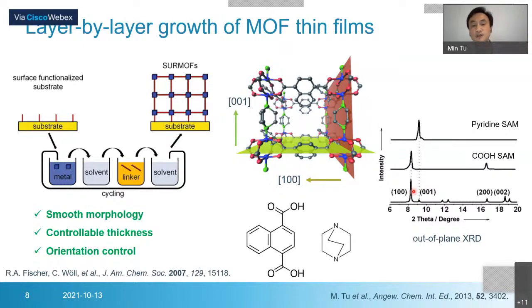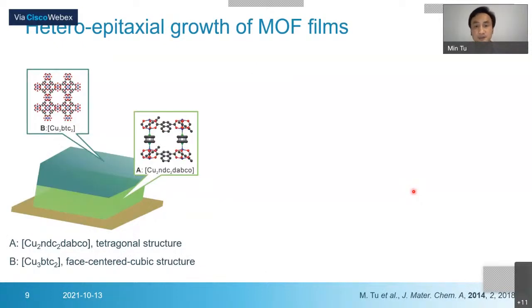By using this method, we can not only deposit single-layer MOF films, we can also work with heteroepitaxial growth of MOF thin films. Basically, we can introduce two different MOF films on one surface, and both of them are grown oriented. For instance, here we have copper NDC DABCO on the bottom, which is a tetragonal structure, where the metal source is copper acetate and the linkers are NDC and DABCO. And the top layer is copper BTC, from copper acetate and benzenetricarboxylate. It's also called HKUST-1. Both MOF systems share the same copper center, but the linkers are different, and the structures are completely different.